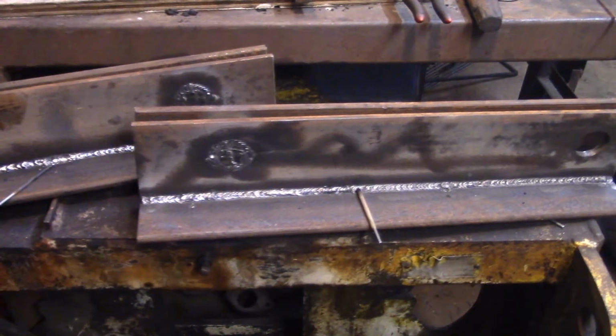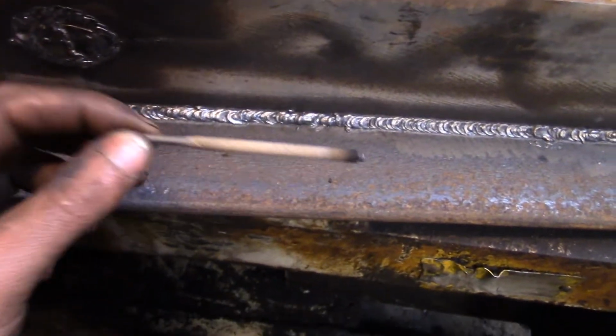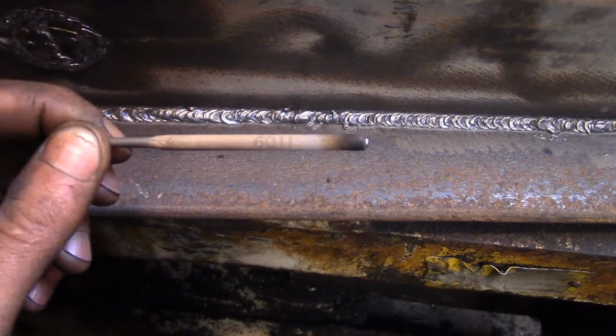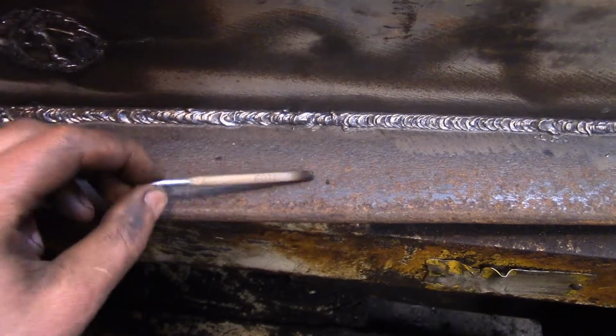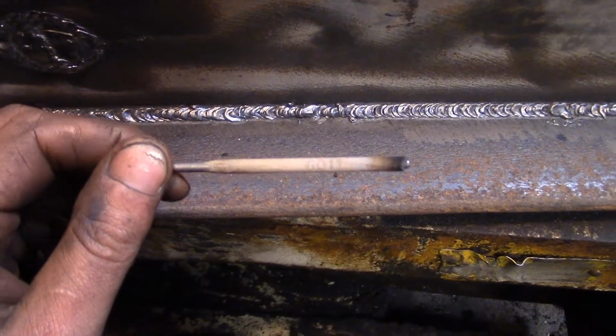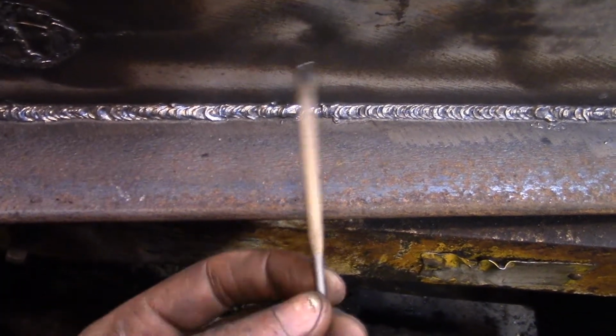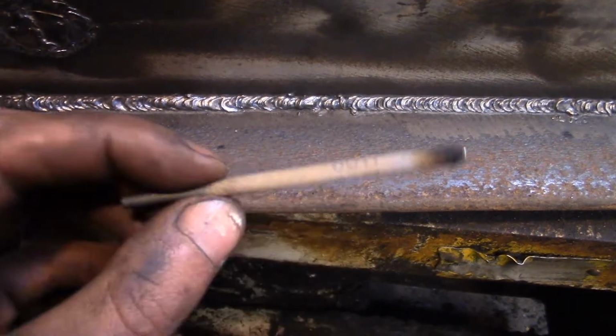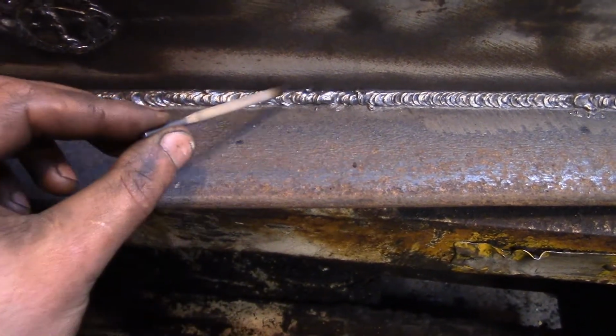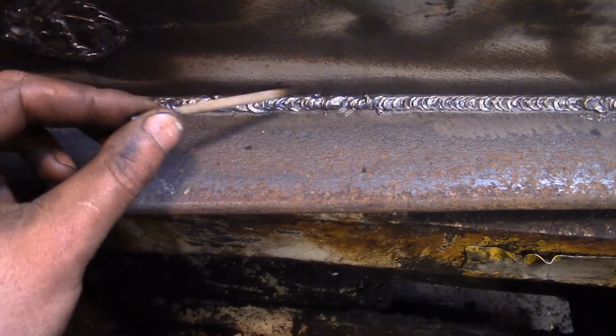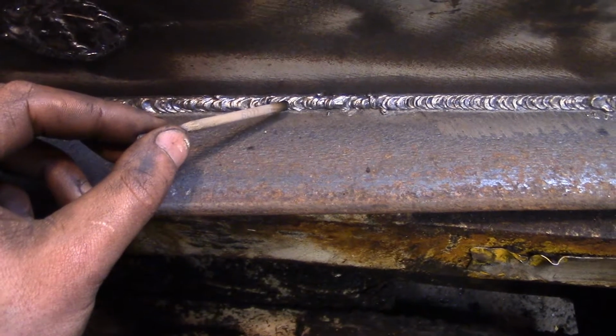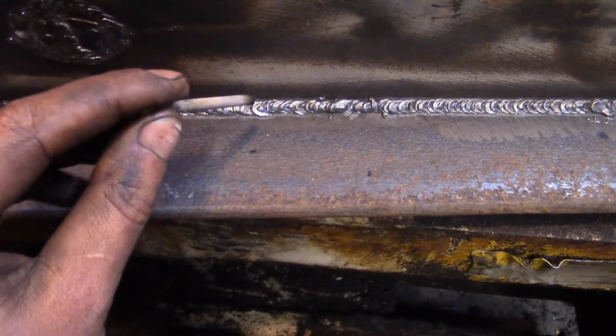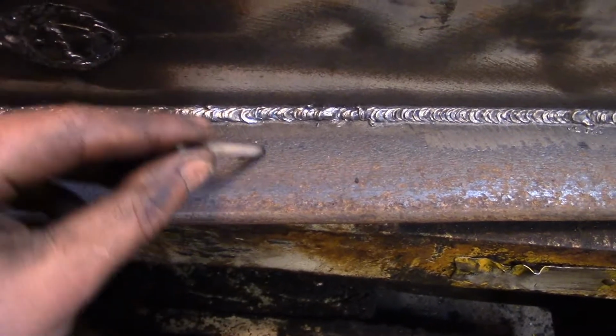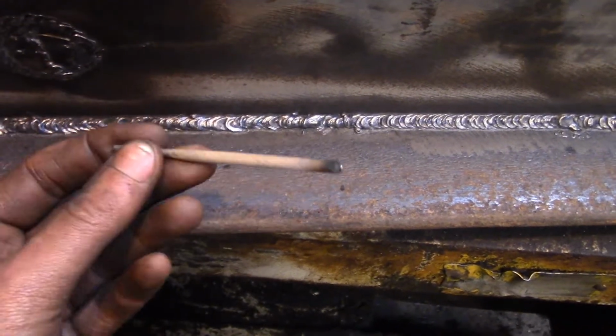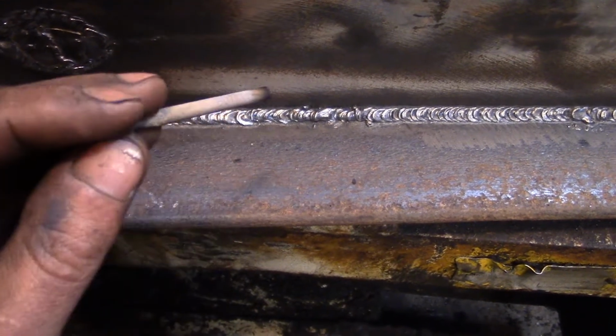The next one is just a little. I tell this to everybody when I'm talking about stick welding. I think 6011 is by far the best rod to use. If I had to use just one rod for the rest of my life, I would choose 6011. It has a very light coating of flux, so when you weld, of course I wire wheeled this, but there wasn't a big fat coating of flux over this, or slag I guess. It cleans off very easily. It digs very well. When you're welding, you can see it just cut a hole into the material you're welding and then fill it back in with molten filler metal. So you know you're getting good penetration.